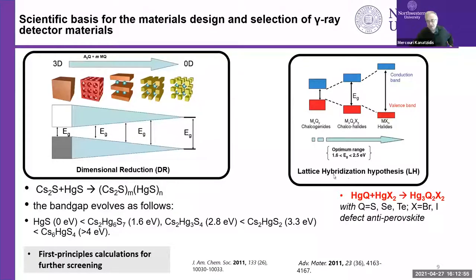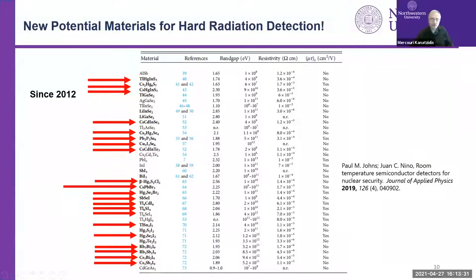On the right, we have something called lattice hybridization. Here we have a metal chalcogenide material like the mercury sulfide, which has heavy elements, but too small a gap. On the other side, we have a metal halide that has also heavy elements, but too big a gap. And so if we make compounds that have both chalcogenide and halide, we may get structures that have an intermediate gap, which is just right. So thinking this way, we discovered many promising materials.